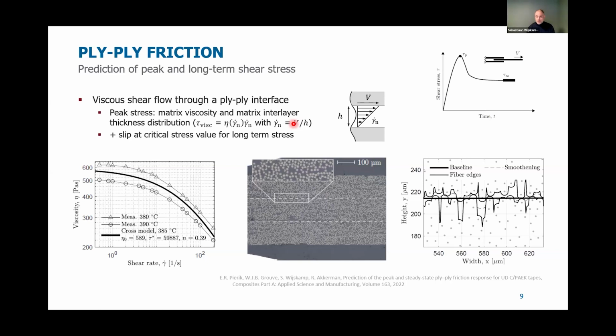So assuming viscous flow between two subsequent layers, where your shear rate is dominated by the distance between the two sliding surfaces, the plies here, and the velocity. It's non-linear viscous, so that means that we need a viscosity. We can measure that using rheometers. We also need a description of the interface, the interlayer between two plies. Here we already put dashed lines, so it now looks quite obvious to recognize the individual plies, but without these it's quite difficult. But it's there, and this interlayer can be described either from micrographs or by simulating them mathematically. So we have a description of this interlayer.